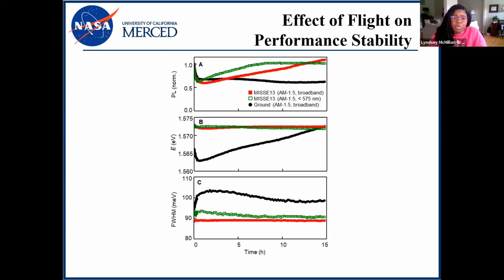Now, here we can explore the stability of the samples and how they behave. This data was taken with constant illumination over the course of 15 hours. The illumination was broadband, and in the case of the data shown in green, that was broadband with a cutoff at 575 nanometers. We selected that cutoff because blue and green light are known to speed up the light-induced degradation in perovskites. So this will elicit a worst-case scenario response.